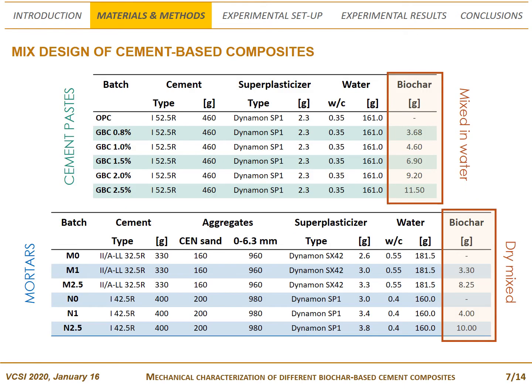Biochar was added in the mix design of cement pastes and mortars by adopting increasing percentages up to 2.5% by weight of cement. As regards cement pastes, biochar was mixed in a solution of deionized water and superplasticizer. Then the ordinary Portland cement was added.